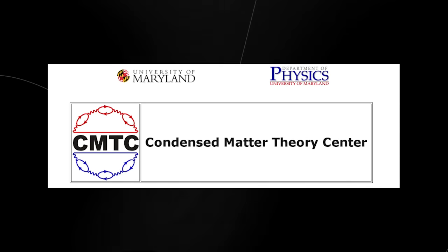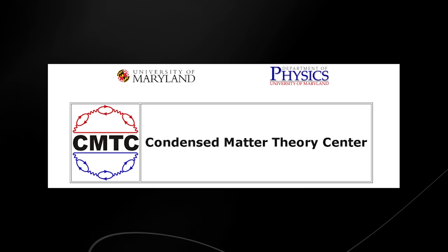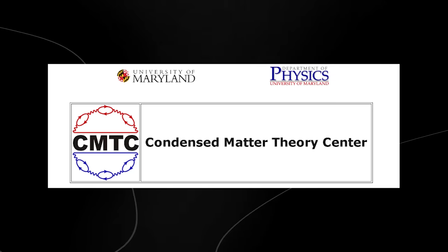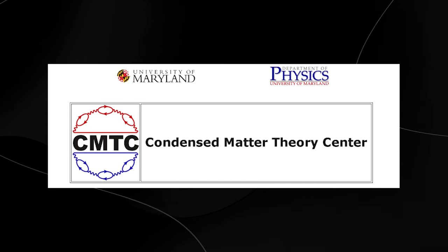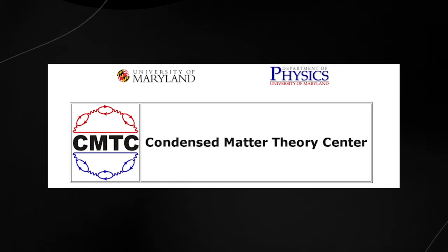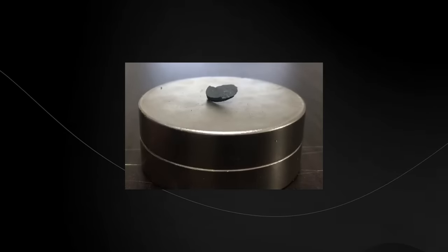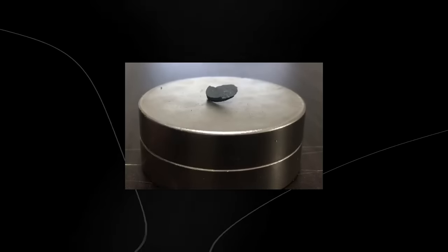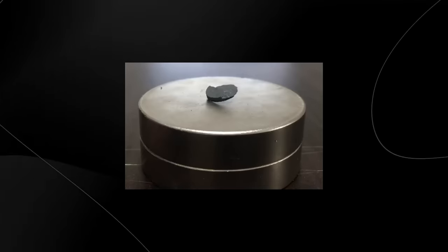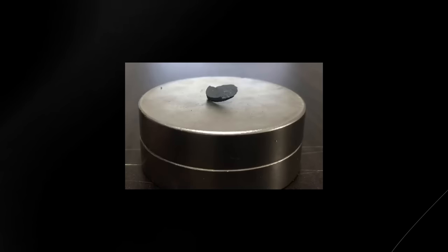The University of Maryland's Condensed Matter Theory Center stated that LK-99 is not a superconductor, even at room temperatures, and described it as a highly resistive, poor-quality material. Another study pointed out that an impurity in the initial samples, cuprous sulfide, could explain some of the observed properties. Despite these counterclaims, some researchers caution against fully dismissing the original claims, as impurities and optimization of factors like composition or firing time may still reveal superconducting properties. However, the consensus among experts is that LK-99 is not a superconductor. At least, that was until recently when this new paper was published.